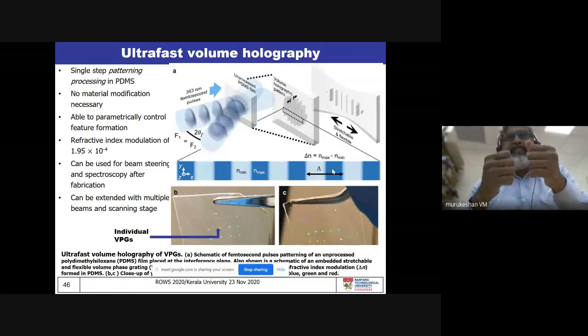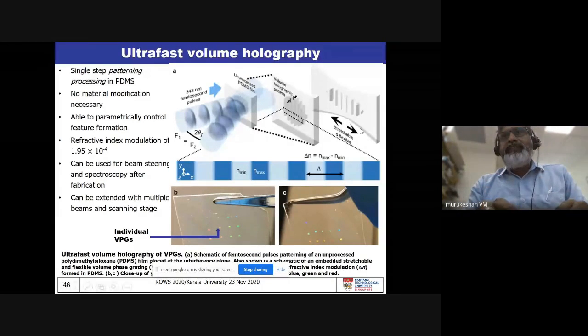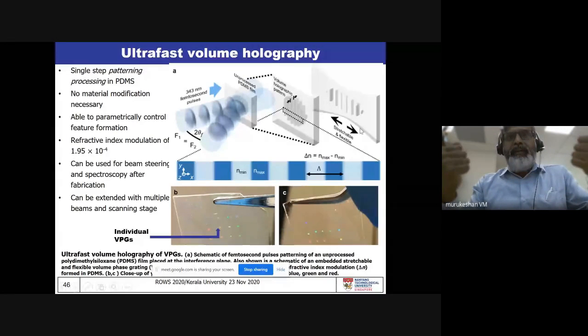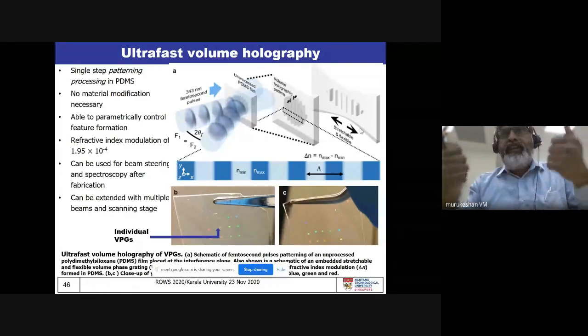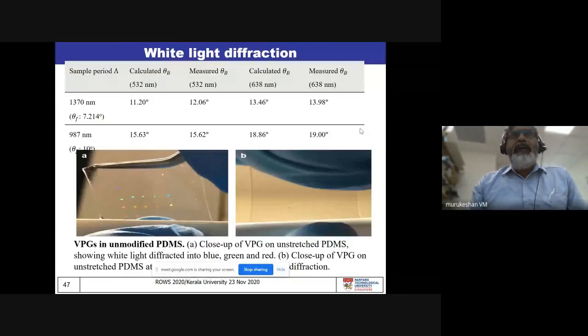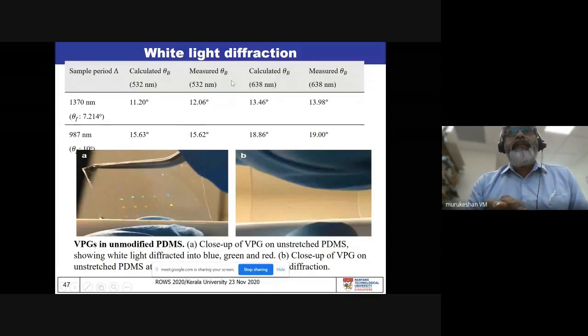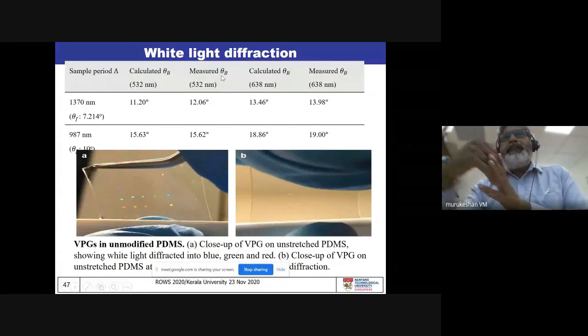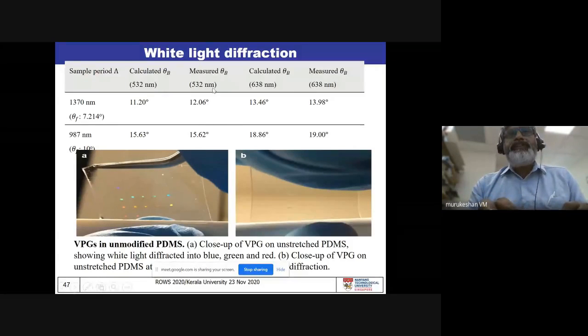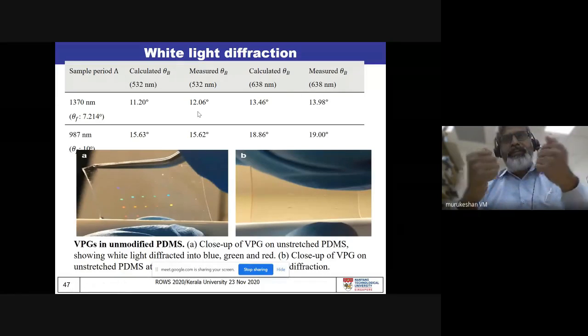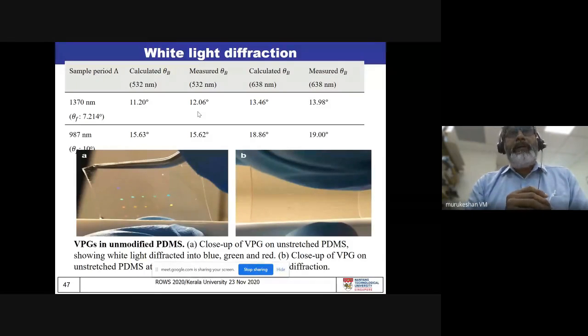And such structures, if you pull like this, you can actually stretch it. And you can see that when you do such a stretching, you can use it for various applications. You can see that you can control the theta, the Bragg angle, for different wavelengths. When you use different wavelengths, you can control the Bragg angle, and the stretching ratio is going to really affect your tunability. And the next slide is actually going to show you that.